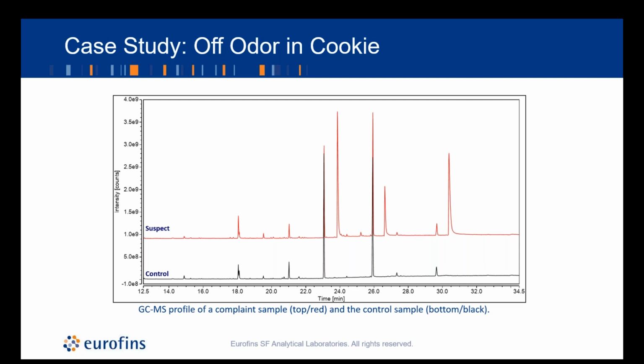So the first thing we look at is this has very clear differences, which is very helpful in this profile set. We look for peaks that are not present in one sample or the other. And we also look at the relative intensities of existing peaks between samples. That means we compare the heights and areas of the peaks that are already present. In this case, we have three very obvious peaks that are present in our suspect sample, and they are not present in our control. And these are caprylic acid, capric acid, and lauric acid.